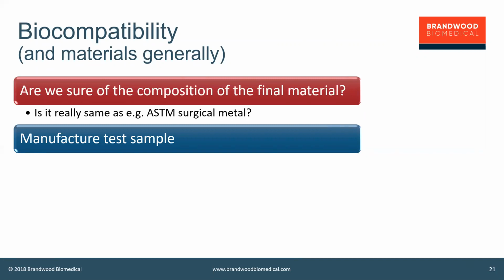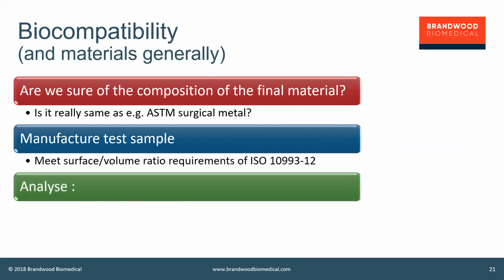doing an extract. And the Part 12 standard in ISO defines the volume to surface area ratio of the test sample that you immerse in the test solvents to do an extract. So 3D printing is great because you could actually print test samples that provide you with the right volume surface area ratio to make it easy. So you can print your test coupons using your additive manufacturing machine. Manufacture the test sample, meet those surface to volume ratio requirements, and then analyze it.